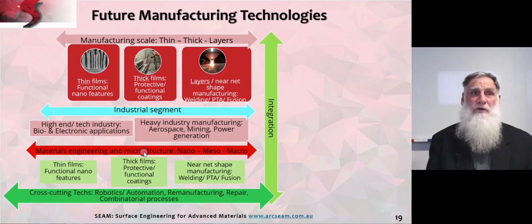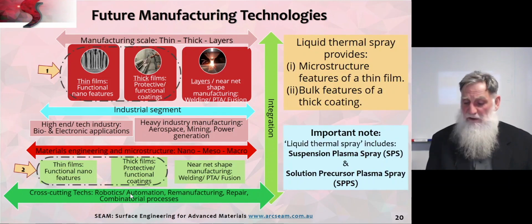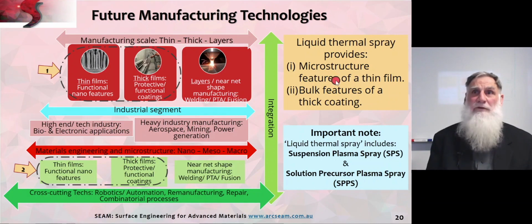And this all depends on the materials engineering of the microstructure, from nano to meso to macro. So for thin films, we have functional nano features, and for thick films, we have protective functional coatings. And all of these can be wrapped up and controlled by Industry 4.0 in robotics, artificial intelligence for remanufacturing and repair. So liquid thermal spray provides the best of both worlds. First of all, the microstructural features are those of a thin film, whereas the bulk features are of a thick coating, as you see in number 1 here. So by liquid thermal spraying, we've got both thin and thick film attributes.